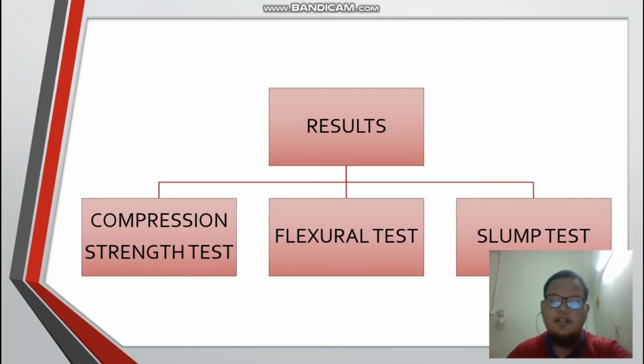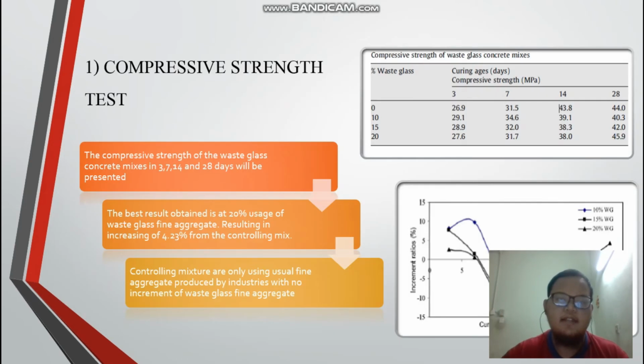Today I will present the study on waste glass replacing fine aggregate. I will present the results, which consist of the compression test, flexural test and slump test. As you can see here, for the compressive strength test, at 20% waste glass at 28 days, it increased by 4.23% from the control mix. The control mixture only uses fine aggregate and no waste glass.